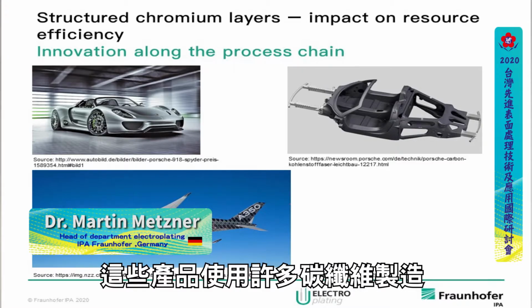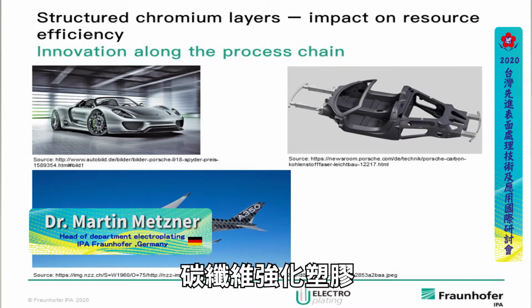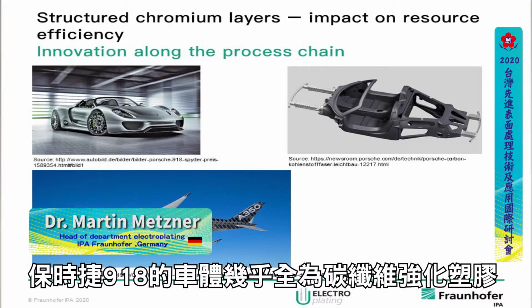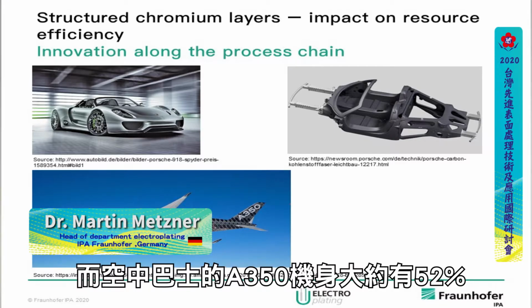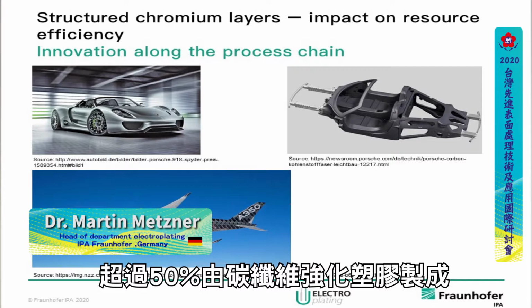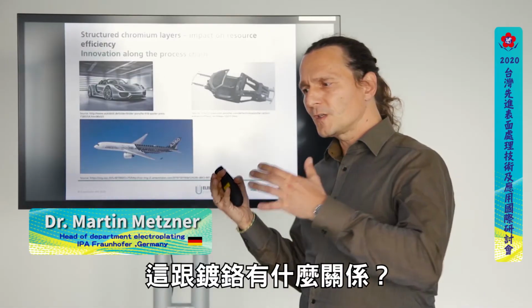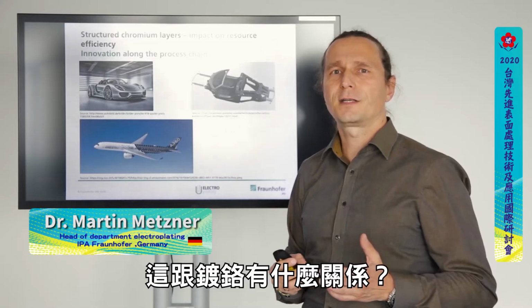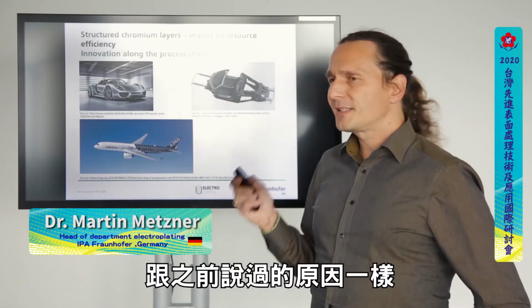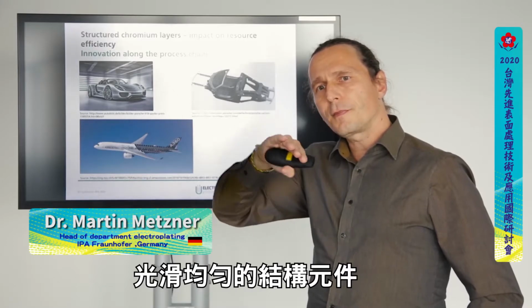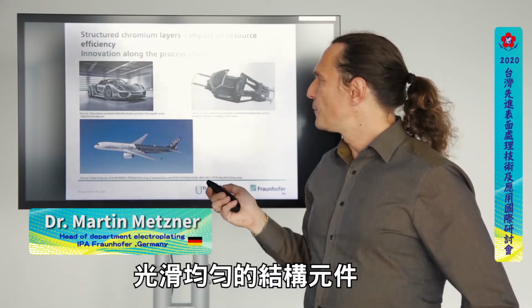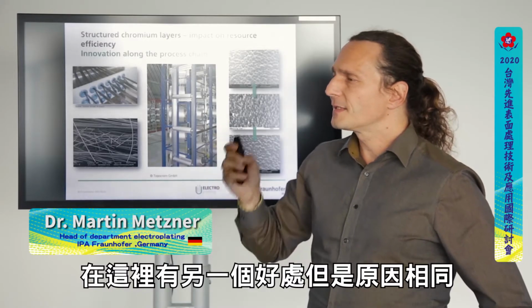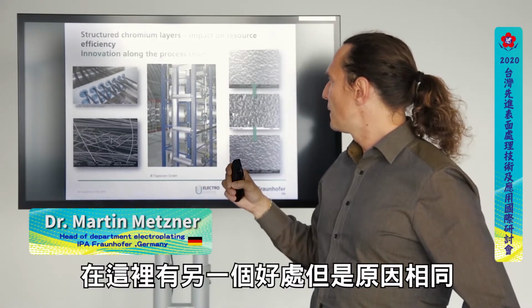And these products are known to be made with a lot of carbon fiber reinforced plastic. The Porsche 918, the bodywork here is more or less completely carbon fiber reinforced plastic. In the A350, I think the bodywork is made for 52% or something like that, more than 50% of fiber reinforced plastic. So what does this have to do with chromium plating now? This is quite simple. For the same reasons I told you before, the smooth structure elements that we have give again the same or another benefit here, but for the same reason.